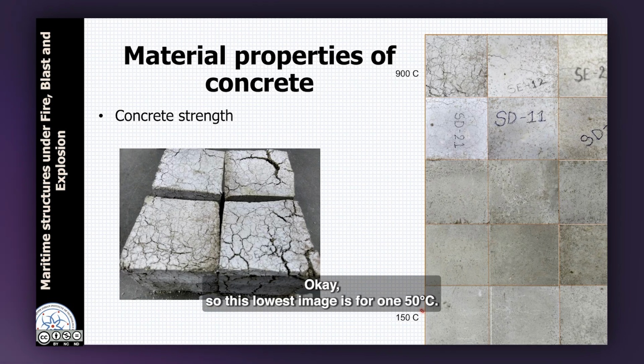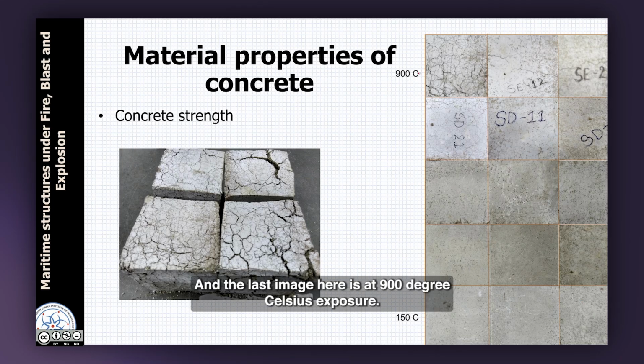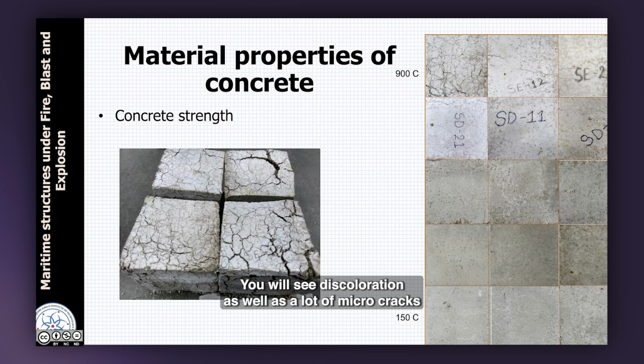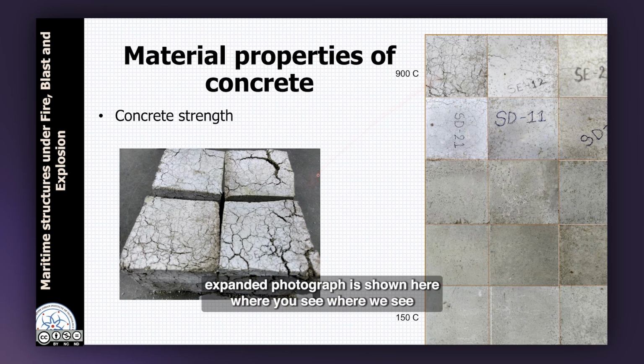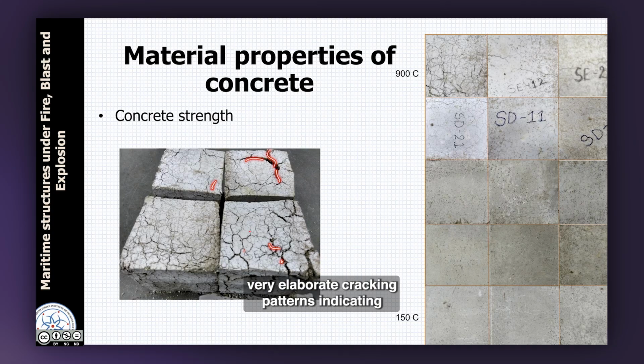Okay. So this lowest image is for 150 degrees Celsius. You will see that there is not much discoloration that has happened, and the last image here is at 900 degrees Celsius exposure. You will see discoloration as well as a lot of micro cracks which have formed. Okay. And an expanded photograph is shown here where we see very elaborate cracking patterns indicating almost zero strength in concrete at this point in time.